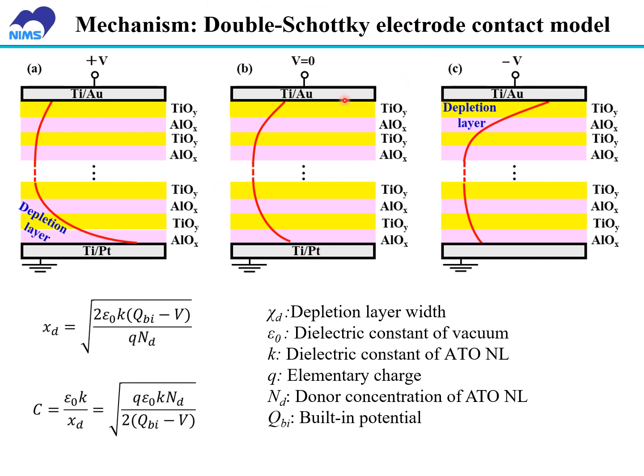Last, I want to discuss the mechanism for the super high dielectric constant of the ATO nanolaminate. As mentioned above, when the ATO nanolaminate is a semiconductor, the dielectric constant is very large, higher than 100. Actually, when the nanolaminate is a semiconductor, we cannot consider it a MIM capacitor. It is just a double Schottky electrode contact model for the devices. When the voltage is positive, with the increase of this voltage, the depletion layer width on the bottom area is very large. In this case, the K value for the ATO nanolaminate increased.